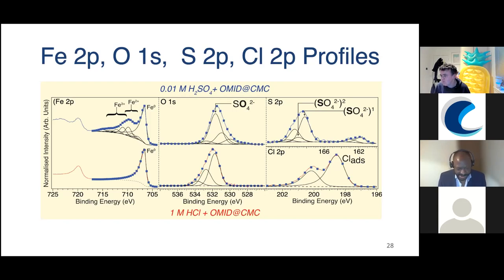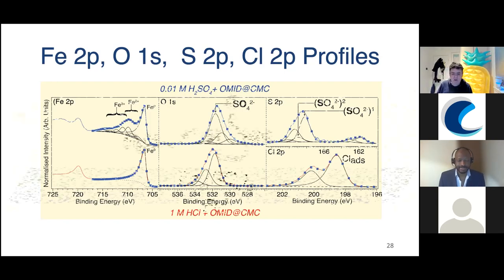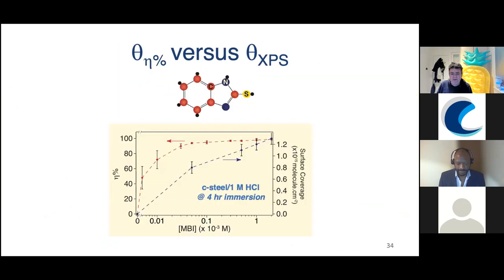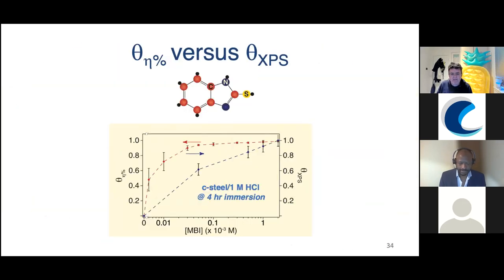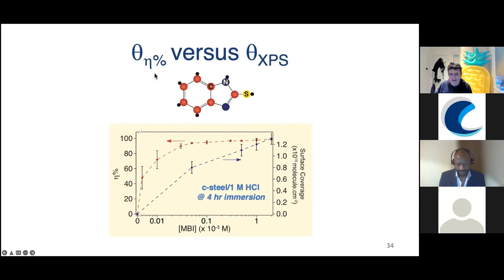Okay, next question we have is from Mehdi. He says, is it possible to study and measure the corrosion inhibitor film thickness by XPS? Yeah, so we didn't do the thickness, but we did the coverage in this case. From the XPS, so this MBI molecule, this mercaptobenzimidazole, we did measure the surface coverage for that.